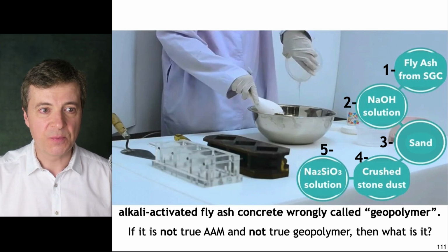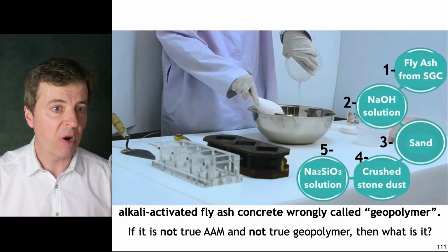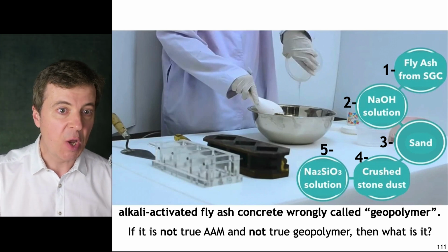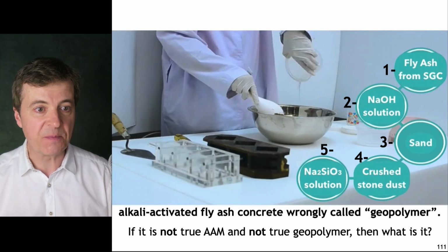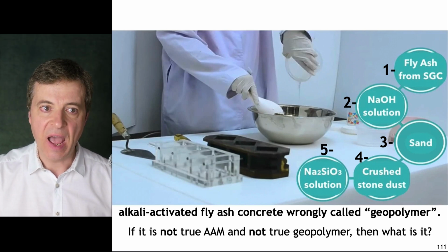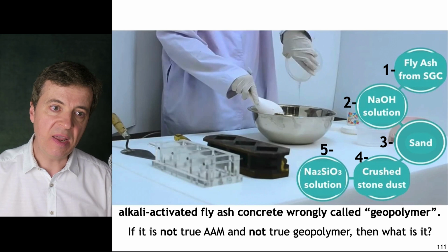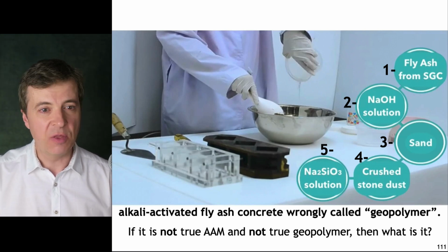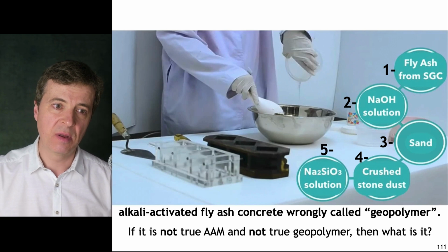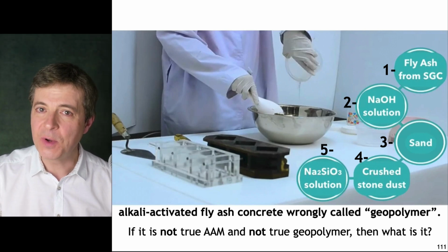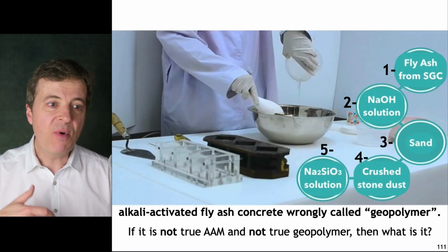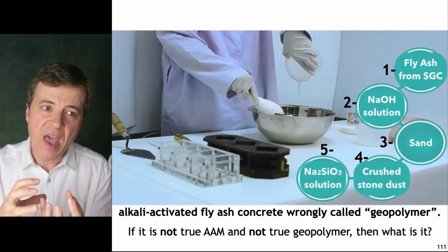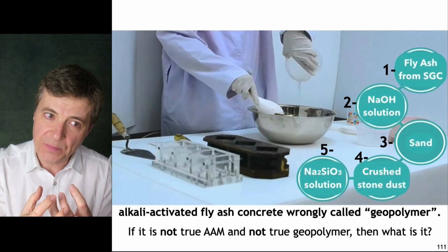Problem number 2. They read that geopolymers use sodium silicates, so let's add some silicates to go along with this new fashion. They add it at the end of the mix, playing the role of a simple fluidizing agent, bringing no reactivity at all. Because liquid NaOH already covers the surface of fly ash, of sand, and crushed stones.